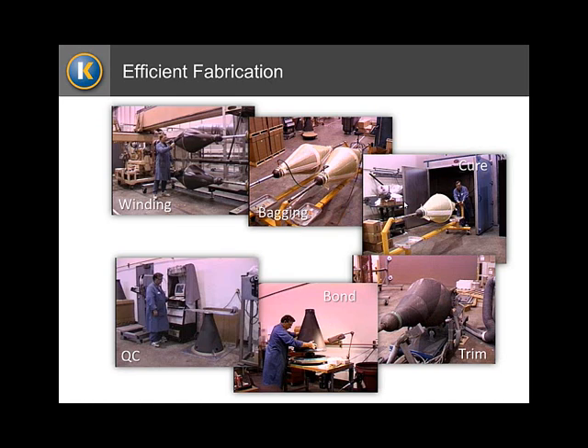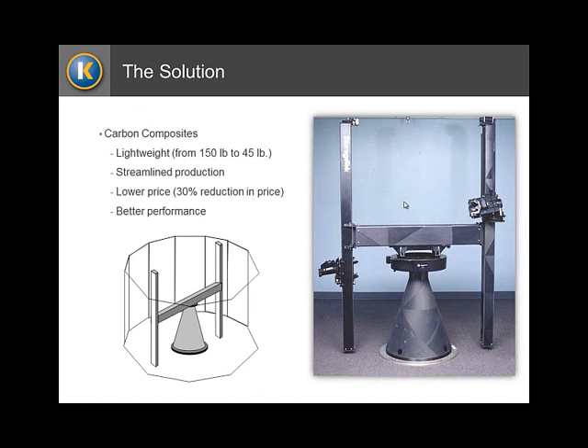The total process to make these parts involves the winding, then what we call vacuum bagging, like I described earlier, to be able to apply actual pressure to the part during cure. We cure it in an oven. We do a trim operation, and then finally we do a bonding operation. And this is really key to make this part successful. We are able to bond aluminum flanges top and bottom of this pedestal at a very precise relationship to each other. So the parallelism was very tight, and that totally eliminated any machining to be done on the part. And finally, there's a QC step to make sure we're in the right frequency range of the parts.